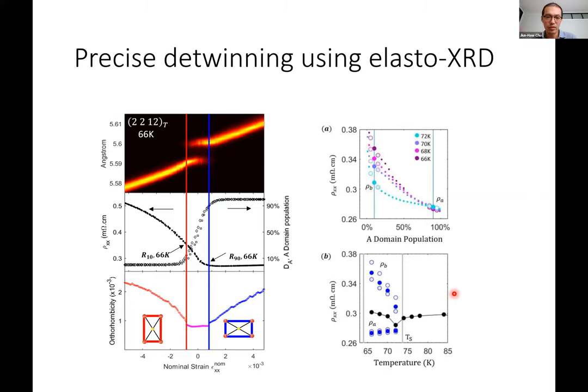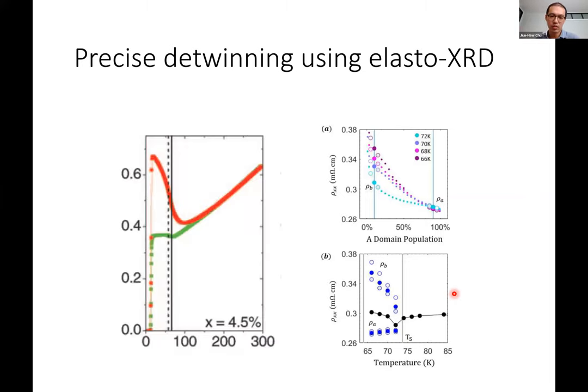So you may say that this detwinning measurement was done 10 years ago, but there's a big difference. For example, in this measurement done 10 years ago with actual pressure, you can see that the resistivity anisotropy is already developed well above the phase transition. And this, of course, is because we're already applying pressure and the crystal is already being deformed. Therefore you're already seeing a mix of the elastic resistivity plus the spontaneous resistivity anisotropy in this part of the phase of the system.